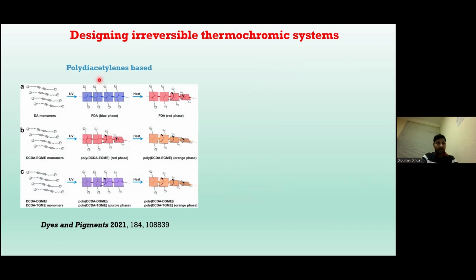Actually, these diacetylene molecules form their polymer structures in the presence of UV light, and they form linear structures actually. And as a result of it, they will show blue or violet color depending on the groups beside these acetylene moieties. And when we apply heat, then their geometry will be changed, and they will convert themselves to stabilize their energy. So that's why the linear structure will be lost, and as a result of it, the conjugation will be lost. So there will be a change in their absorption, and eventually they will show a different color.